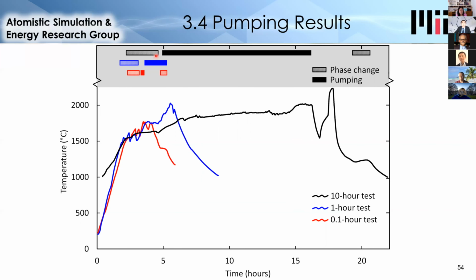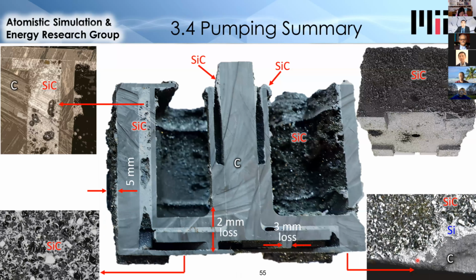So in the longest test where the pump was used for about 10 hours, or at least rotating, this test went on, but at the end of the test, the pump shaft got stuck, and throughout the test, the ability to measure the flow rate was degraded, and afterwards, it was very obvious what the problem was. So if we look at this figure in the center, this is the pump cut in half after the test. If we follow the flow path of the silicon up from the bottom, out to the side, and then up this path, you can see this path is completely clogged with silicon carbide.